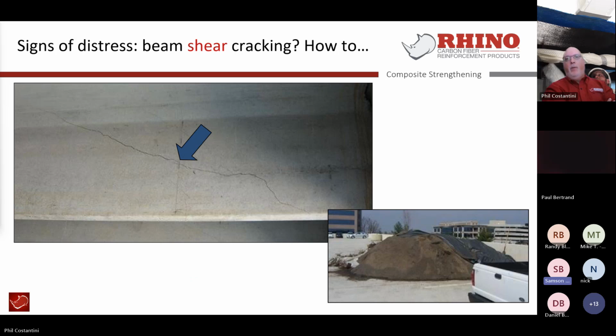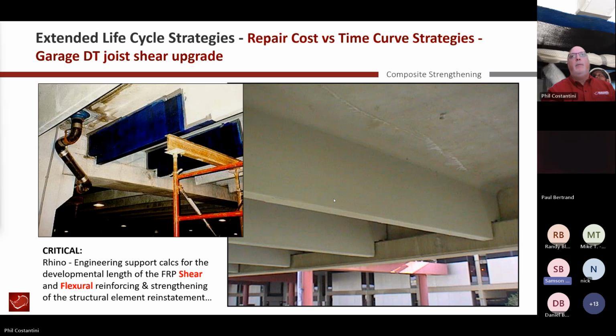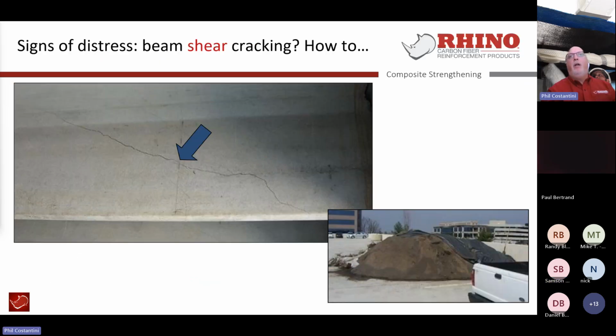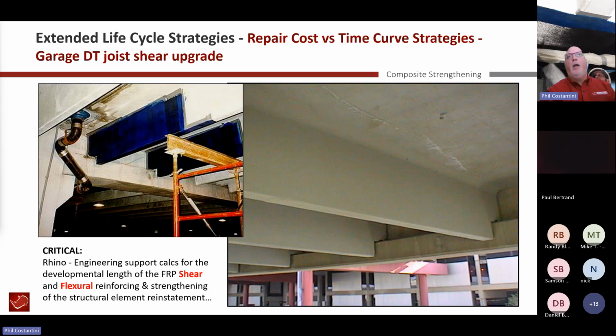I see. Okay. Thank you. So it's the classic prescriptive method. It's still a crack. A crack is a crack is a crack. In a structural member like that, we're not going to let it stand alone. The bond line has to be reinstituted with epoxy, and then we can get to this. Got it. Thank you. Now, could it have just been solved with an epoxy? Probably, because there was no displacement, but the engineer of record wanted a backup, and this is the backup.